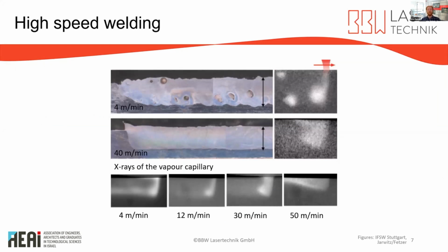Another possibility is high-speed welding. This also reduces several weld irregularities. And again, some X-ray analysis from the IFSW Stuttgart. We see here a widening of the vapor capillary, which leads to a more stabilized capillary itself. And fluctuations of the capillary decrease with increasing feed rate, and the capillary opens more. And at 50 meters per minute, there is a completely different geometry. This could be a huge presentation itself about this topic.